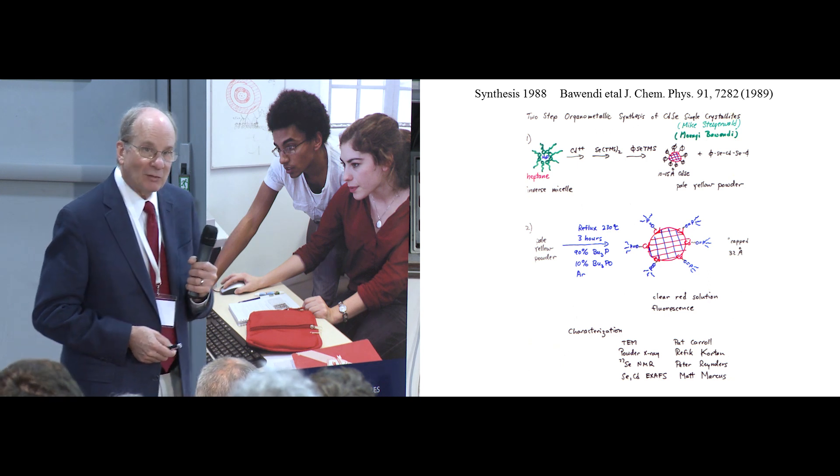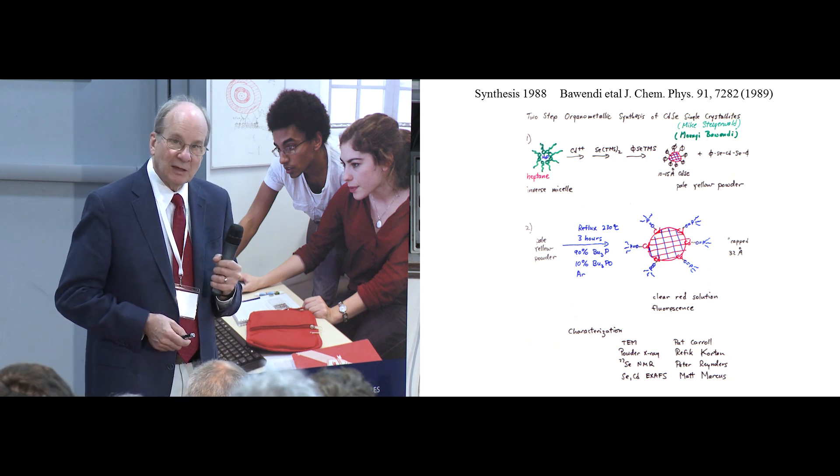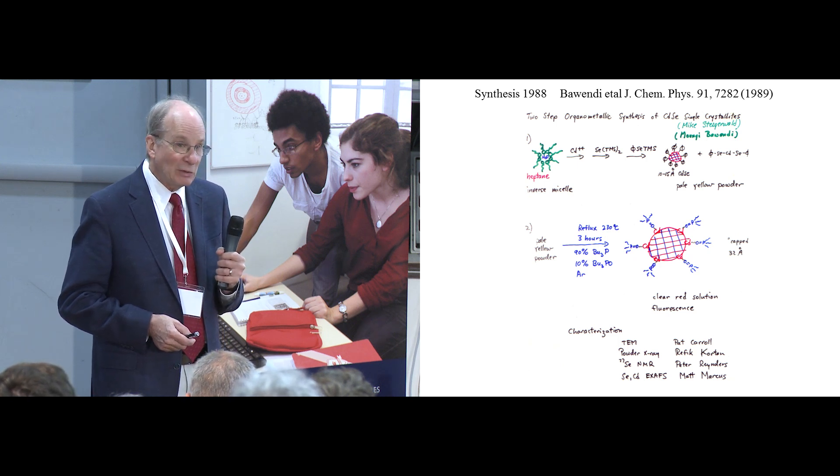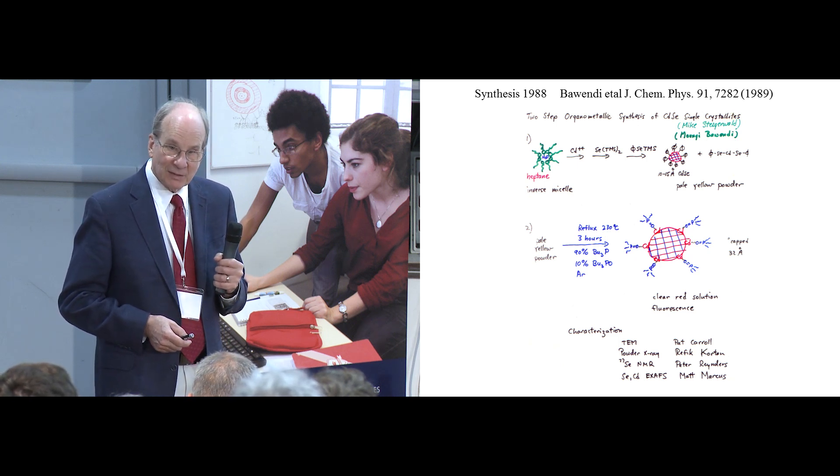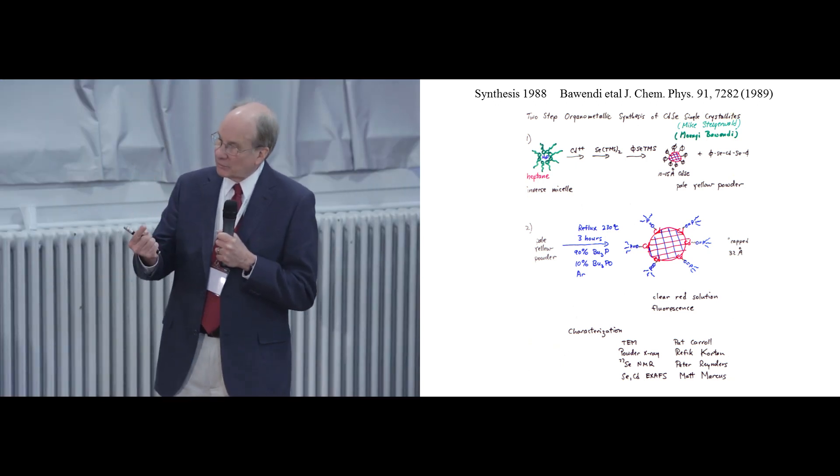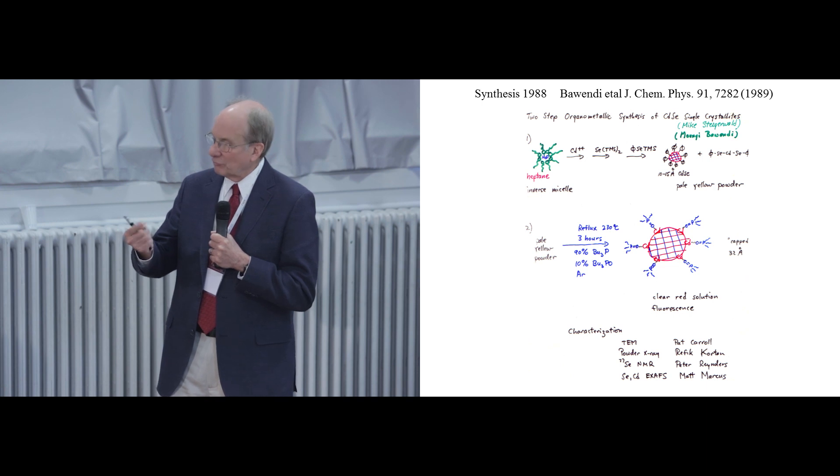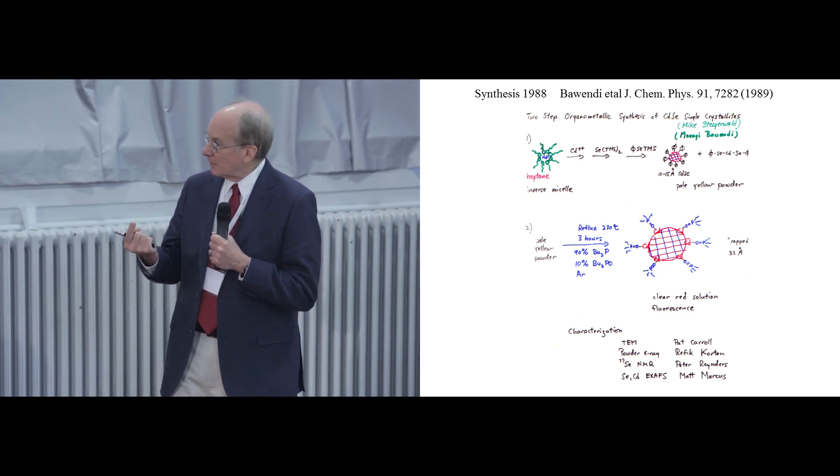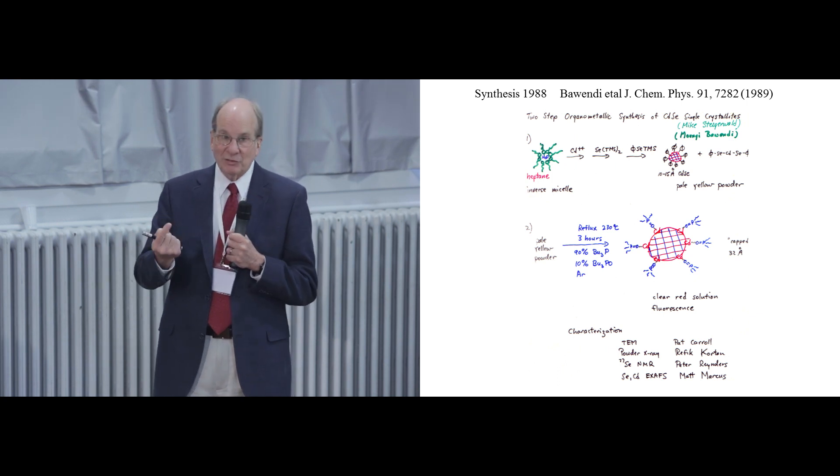And more of it did dissolve all right. And the color changed a little bit when we refluxed it in pyridine. Then we took the optical spectrum a second time, after we had refluxed it for a while in pyridine. And I remember being amazed when this exciton peak sharpened up. That was the first time I had any sense that temperature was important.